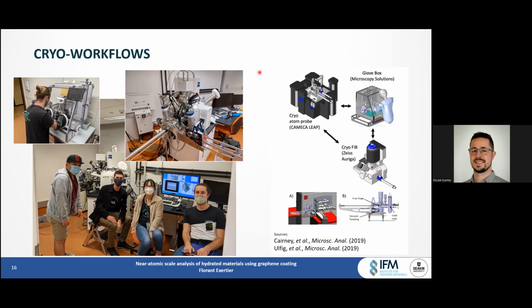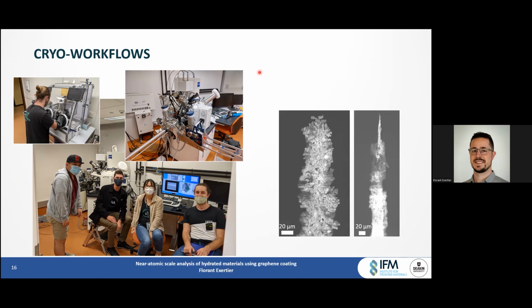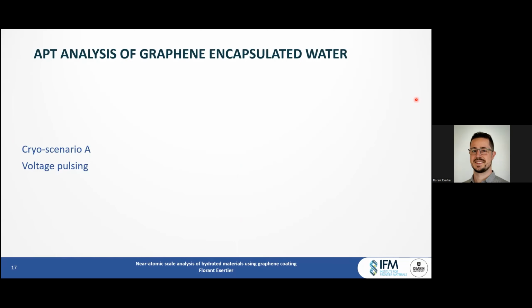So first overview of the cryotransferred samples was, well, unfortunately, some tips were covered in frost, as here on the left. But since we were using the FIB, we were able to remove some of the frost and hopefully target the tip of the specimen and remove the graphene, which was achieved by Li Mei. And so here is an overview of the atom probe results from a sample analyzed in scenario A with voltage pulses, meaning that, again, the sample was plunge frozen following graphene encapsulation and then transferred directly to the atom probe and analyzed.